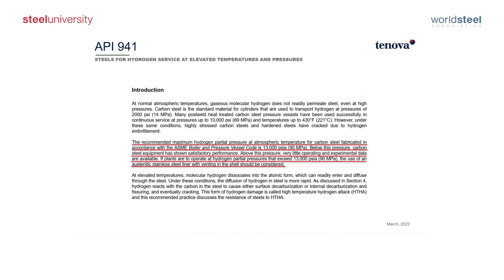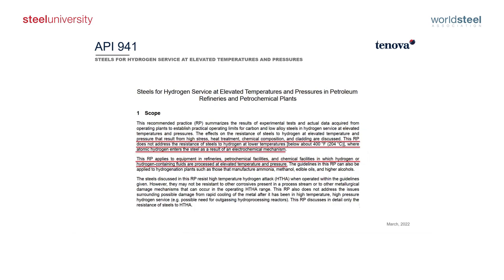There are, on the other hand, limitations on the operating pressure, depending on the quality of steel that you use for your construction. Again, the point is hydrogen tends to diffuse into the metallic matrix and modify the mechanical properties of the metal, where the metal gets saturated with hydrogen. This causes a special kind of corrosion. But this diffusion happens only if a certain threshold of temperature is passed. So we are talking of 90 MPa, meaning 900 bar, at ambient temperature, and high temperature, above 200 degrees. The combination of these two factors, very high pressure and temperature, results in diffusivity of hydrogen into the metallic matrix and this kind of corrosion attack.